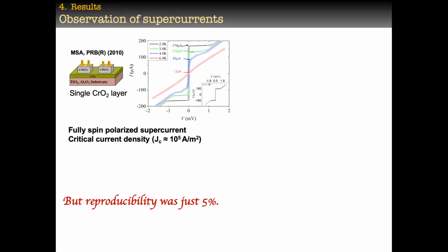With this idea, I started new devices again, and here you can see that we successfully observed this supercurrent, which is fully spin polarized. But again, the reproducibility was just 5% because chromium dioxide is in a metastable state. It can easily convert into chromium sesquioxide, Cr2O3, which is an insulator, and that is a problem. The length of this junction was around 800 nanometers. It was the longest ever achieved, so it is still the world record. This is actually in my hands, alhamdulillah.